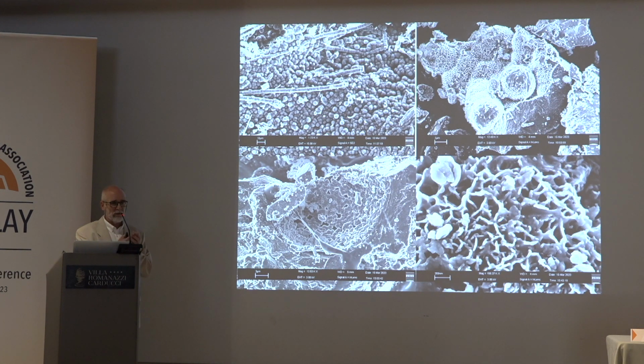But in addition to the filaments, another characteristic feature is the spheres. In some areas of the sample, there are a lot of spheres, quite homogeneous inside, about 2 microns. The spheres also coalesce with one another. There is no separation between them. Some are also coated by plates. You see here a detail of the plate. This is 200 nanometers, so the thickness of these curved folded layers is maybe 10 or 20 nanometers. And these spheres we observe in cavities, in some cases lining cavities. So we deduce that they would precipitate in a confined environment, in areas where the fluid flow was reduced. So I remember I told you about the dynamic of the porosity.